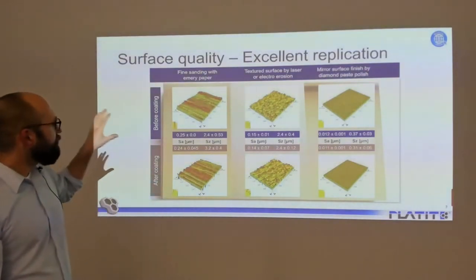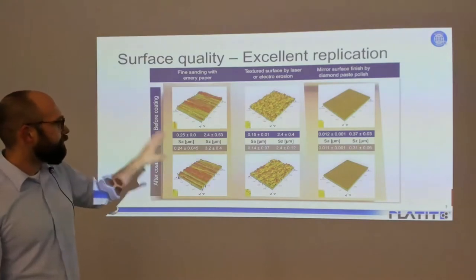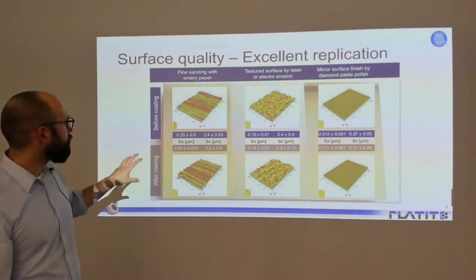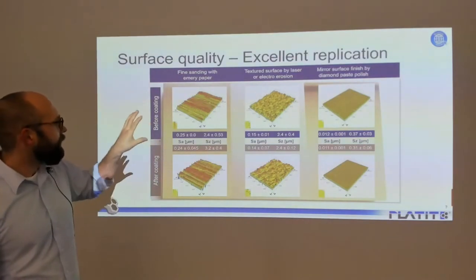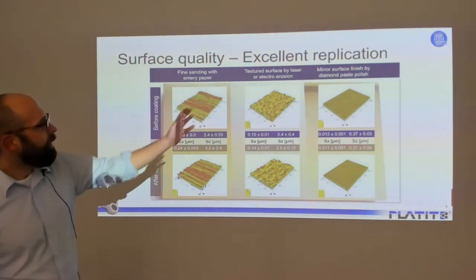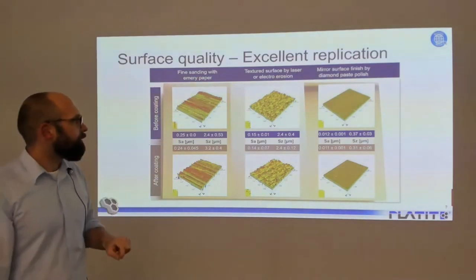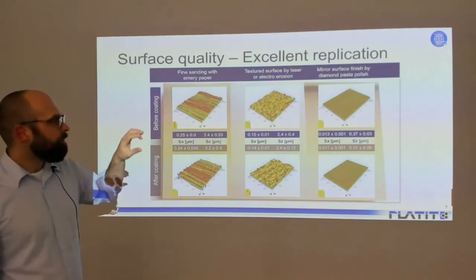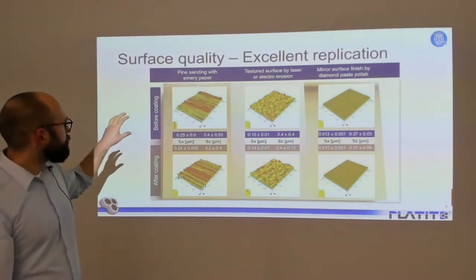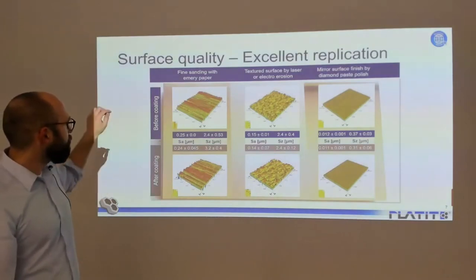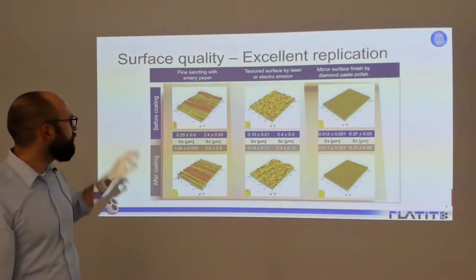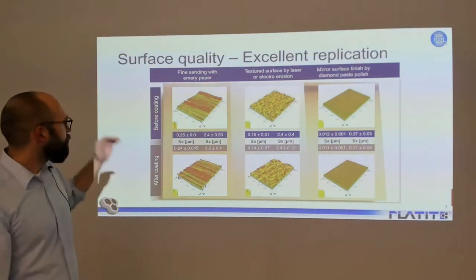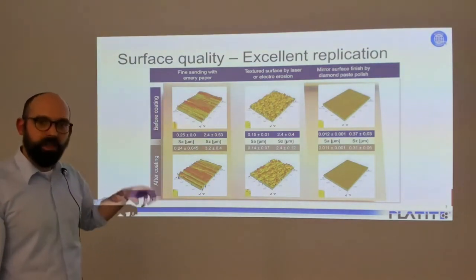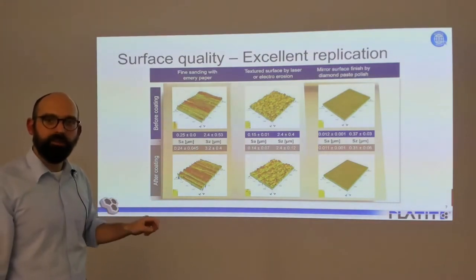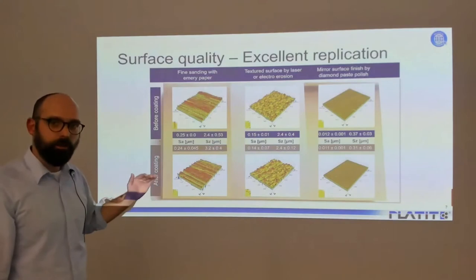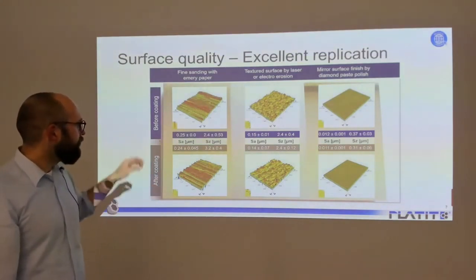Here in the back, you see a steel plate which has received 3 different surface treatments. On the very left, we have a finely sanded surface with emery paper. In the middle, we have an electro-erosion textured surface. And on the far right, you see a surface which has been mirror finished with diamond paste. We use the confocal microscope to measure the surface roughness in a relatively large area, 250 by 250 micrometers, on every one of those segments. Then we took the steel plate, put it in the S-impulse, and coated it with 2.5 micrometers of chromium nitride. And then, after the coating was finished, we took the plate out and measured again.